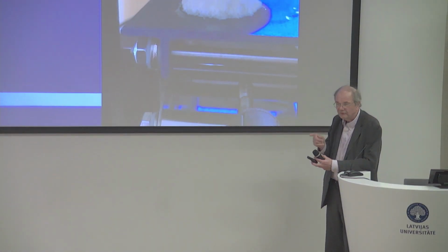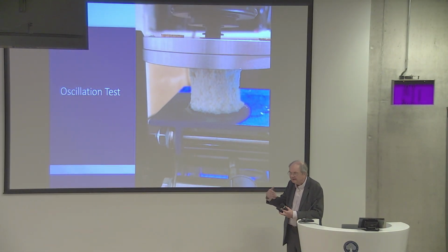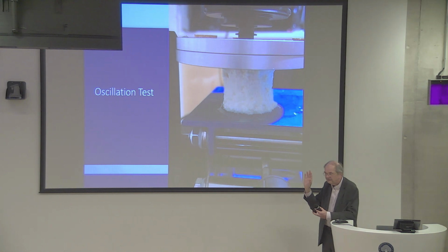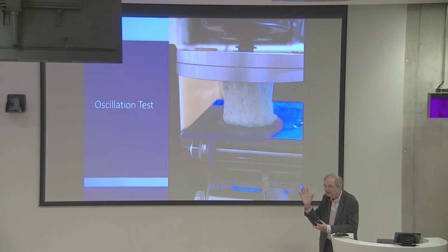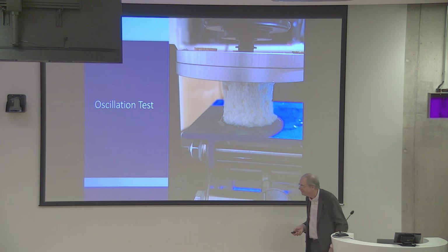And the big advantage of these oscillating pendulum things is that you don't have to measure the force yourself directly. In most instruments, they're expensive and complicated because you have to both measure deformation accurately and you have to measure force or torque accurately. Here you don't have to measure the force, you just have to start the motion, and the force is all provided from the material you're measuring. All you need to do is measure the resonance frequency.